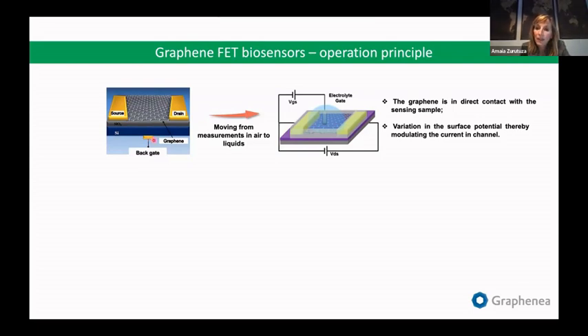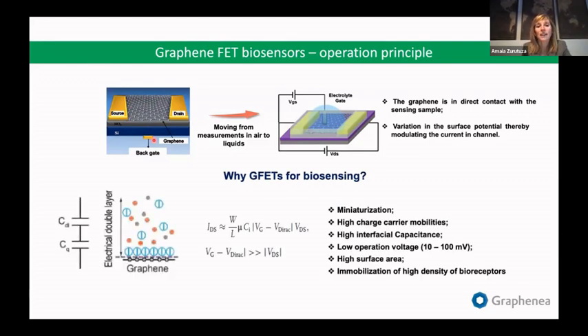If we check a bit the equations behind these transistors, here is the drain-source current, and we want to maximize that. How can we maximize it? By making the device smaller, which is really possible with graphene. It's very easy, you can make the device as small as you want. Of course, it has to be large enough to be able to put the drop and to wet the graphene. But in principle, you could use micro droplets and make a very small device. That way we could enhance the performance of the transistor.